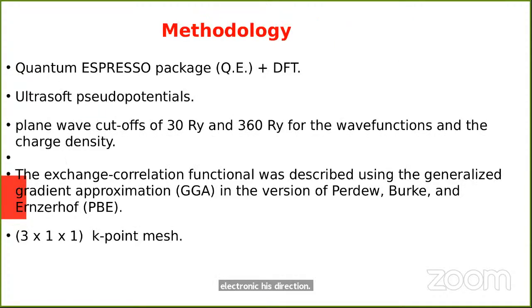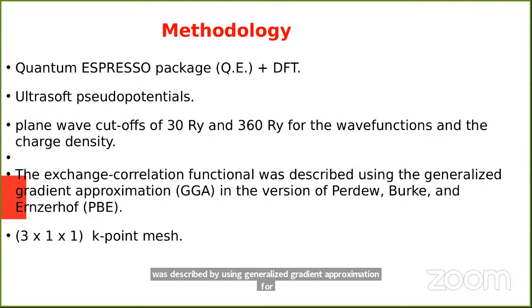For the methodology, we use the Quantum Espresso package with DFT. For the pseudopotential, we use an ultrasoft pseudopotential and a plane wave cutoff of 30 Ry and 360 Ry for wave functions and charge density. The exchange correlation functional was described by using the generalized gradient approximation. And for the k-points, we use a 3 by 1 k-point grid.